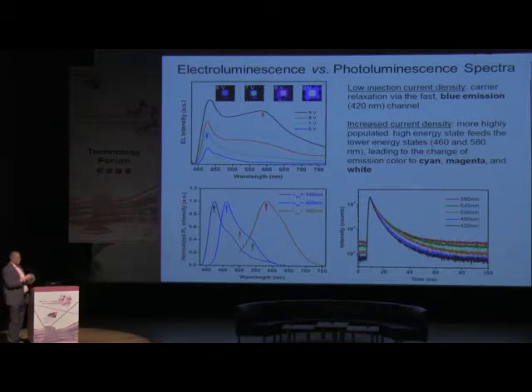That's also related to the spectral profile of carbon dots. You can see here it is quite broad, and if we inject current at low injection density, then the blue emission, this channel here, prevails. We have done some studies where we compare electroluminescence with photoluminescence, and again I remind you that photoluminescence of carbon dots can be moved over a broad spectral range depending on the excitation.